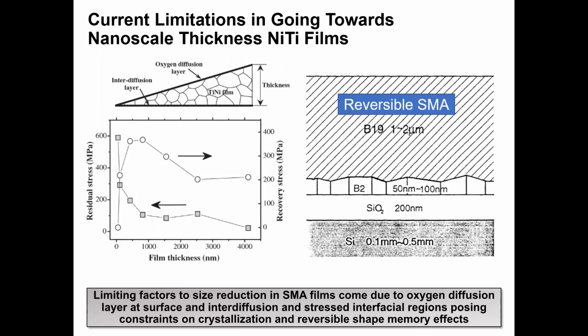So in pursuit of the size reduction in these nanoscale thickness SMA films, which would aid in actuation speed improvements, there does exist some imposing constraints, and those are shown here graphically. So interfacial diffusion regions exist at the NiTi silicon substrate interface, and this is due to the high temperature processing required to crystallize the SMA. And these factors can hinder shape memory effects in these localized regions. Also, the oxygen diffusion layer at the film surface is also crippling to shape memory effects because it changes the local composition of the nickel titanium alloy, which imposes additional interfacial constraints on the transformation or lowers the transformation temperature altogether.